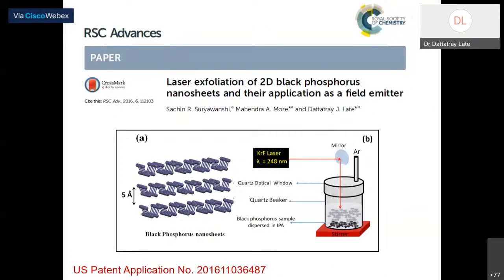Okay, suppose you don't want to wait for 3 hours, so you can have your experiment in just 1 minute. We have used a laser exfoliation experiment for some other materials, for example black phosphorus. We also use it for MoS2, not shown here. So what we need is again bulk powder of any of these 2D chalcogenide materials like MoS2. We need a glass beaker. We need a glass optical window because I need to pass the laser through this glass. Okay, so what we need is some kind of solvent. Here I have IPA as a solvent,